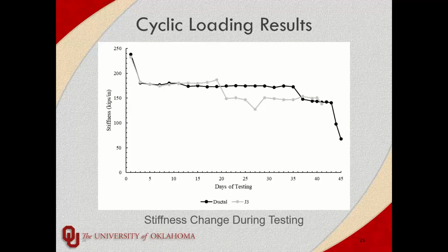And this plot is based on the stiffness. Each dot represents the stiffness of the middle of the day during the cyclic test. So what we would do is we would download the data from the cyclic loading, and we get the slope of a certain amount of time in the middle of the day. We'd average it all, and then it would give us the stiffness value for that day. We plotted both J3 and Ductal, and we noticed that for the most part, they perform very similarly. And this is the misfortune, I think, in this test. And these tests take about 3 months to run. So unfortunately, it wasn't something that we could easily redo.